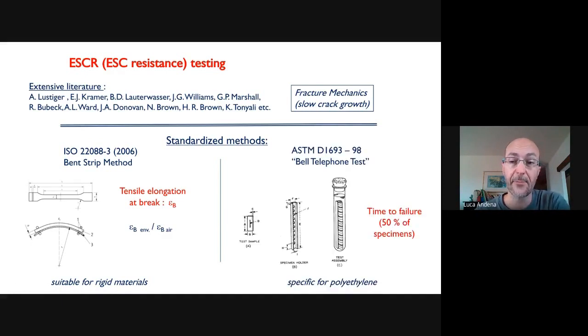Another method is the generally accepted gold standard for polyethylene and polyolefins in general. It was developed in the 1950s by the Bell Labs. And the idea is, well, they were working on cable insulations. The idea is to cut small samples, put a notch in a sample, then you bend it, put a stack of these samples in a vial containing the liquid, and then you record the time which is required to obtain failure in 50% of the specimens.